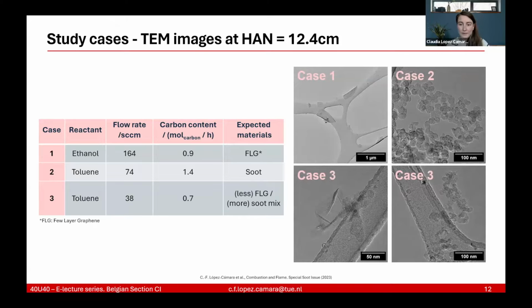And for case 1, we saw these flakes. So basically what you are looking at in the picture of case 1 is the TEM mesh, so lacey carbon. So if you see this very nicely structured carbon, that's not our sample. That's just the support where our sample was being fixed by thermophoresis. So basically by the difference in temperature, our sample was being deposited there. And our sample, what it actually is, is the flakes that are on top of it.